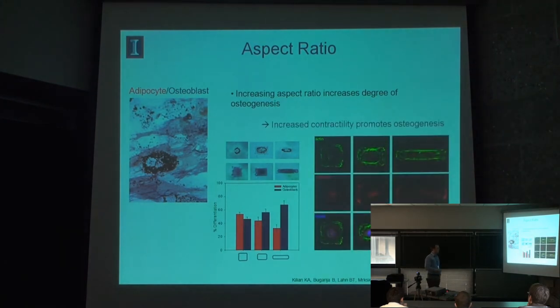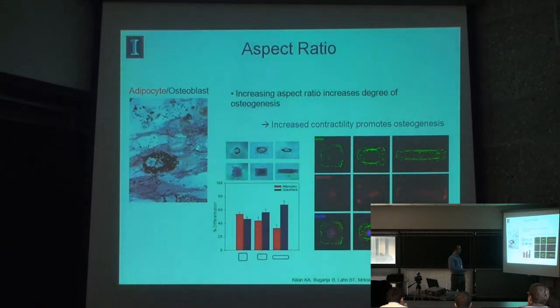And so we went to explore why this was, and one of the things that really stood out was that as you increase aspect ratio while keeping area constant, so there's no difference in spreading here, we see an increase in cytoskeletal tension, where now we get very large stress fibers along the long edge of the cell with more focal adhesions on the short end. And so, similar to the spreading, we have an increase in actomyosin contractility in these geometries, which seems to be a cue to promote bone cell fate.